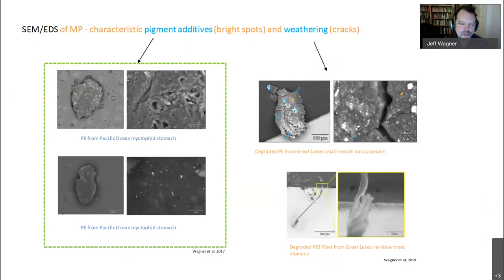This then becomes a very useful screening technique because one can very quickly scan a sample, hundreds, thousands of particles, to find potential candidate microplastics that then can be identified with other microspectroscopy techniques, such as FTIR or Raman. Also on the right-hand side of the screen, you see example of the kind of weathering you can see with using a higher spatial resolution technique like SEM. For older microplastics that have degraded in the environment, you see these characteristic cracks and fraying of fibers like you see in these two images.